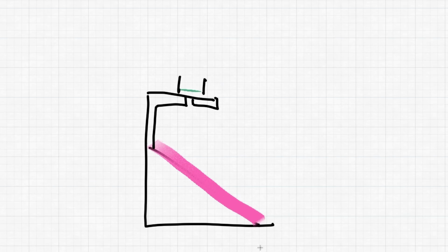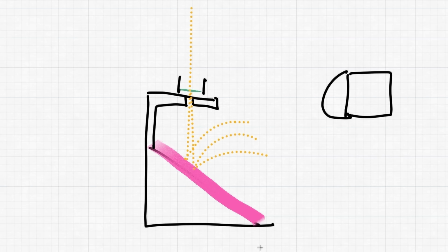We shoot a beam of electrons at our sample, and because this sample is very thin, most of the electrons will pass straight through it or might deviate slightly as they interact with the sample. They'll hit this metal plate. It generates a lot of secondary electron events, and these electrons will just be emitted and are kind of floating around the chamber, which can then be picked up by our secondary electron detector.